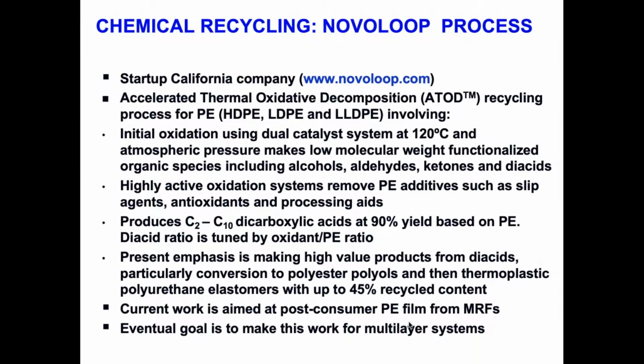And produce especially a range of dicarboxylic acids, C2 to C10, at 90% yield based on the PE, and you can tune this ratio of diacids. Their present emphasis, though, is making high-value products from the diacids, and particularly conversion to polyester polyols and then to thermoplastic polyurethane elastomers, which have up to 45% recycled content. And this is a very good example of upcycling. You have polyethylene waste, which might be worth 75 cents a pound, and they're converting it into thermoplastic polyurethanes, which are probably selling for around $15 a pound. Their current work's aimed at post-consumer PE films from MRFs, and eventually they want to make this work for multi-layer systems.